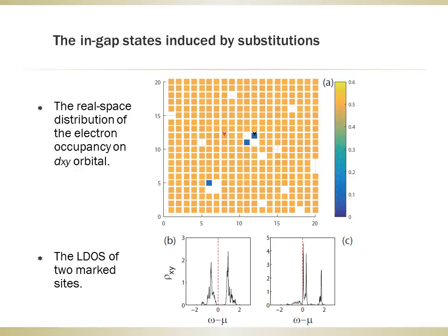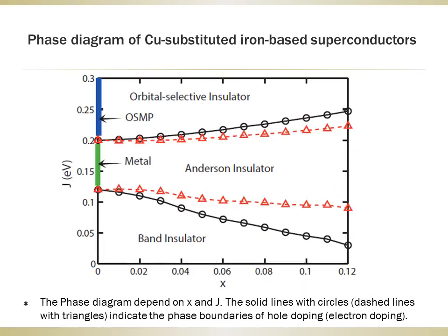The Mott gap is replaced by a sharp peak near Fermi level, which forms the in-gap states in the density of state. It is worth noting that these in-gap states are all localized, which can be confirmed directly from its origin. We compile all our findings about the cooperative effects of the Hubbard coupling and the doping-induced disorder in